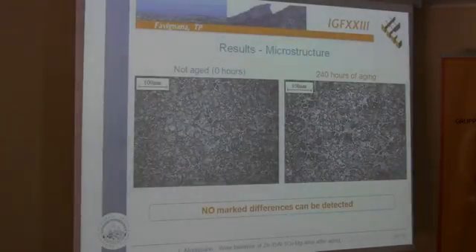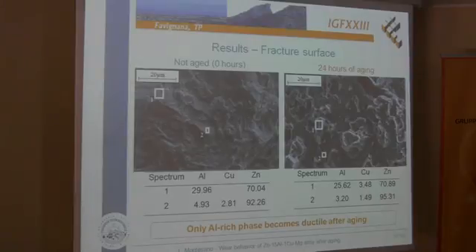To understand the cause of the reduction in mechanical properties, we studied the microstructure of the alloy. As you can see in the picture, we can see two different phases. There are the globules of the primary aluminum phase in gray, and in white the zinc-rich phase. After the aging, we did not point out any substantial modification, neither in the type of phases nor in the morphology or the amount of the different phases. So we moved on to studying the fracture surface of the tensile test samples.